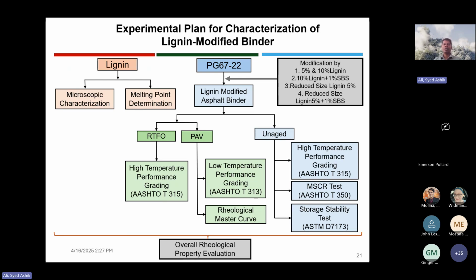So the way it worked is that we wanted to replace 5% or 10% by weight of the binder with lignin. If we wanted to make a 100 gram modified asphalt binder, we took 95 gram of asphalt binder, and the rest 5 gram was lignin. So that's how we worked.